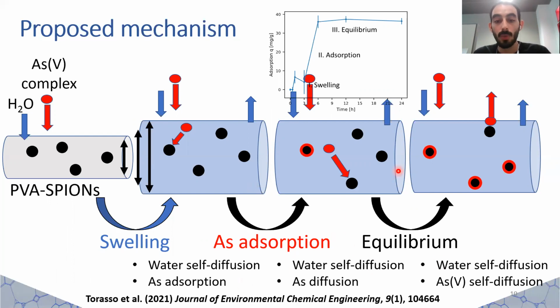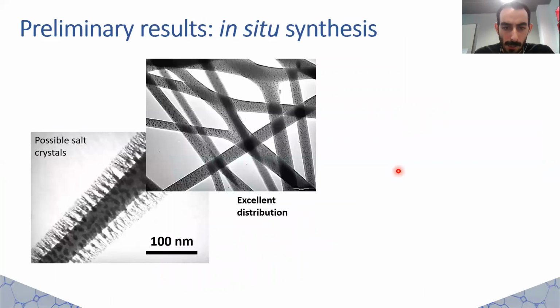What about in situ synthesis? Here we show preliminary results obtained for the in situ synthesis approach. We can see a greater amount of nanoparticles inside the PVA matrix and a possible salt crystal growth. There is an excellent distribution along the fibers, and this is an important issue because agglomeration would reduce active sites on the magnetite surface.